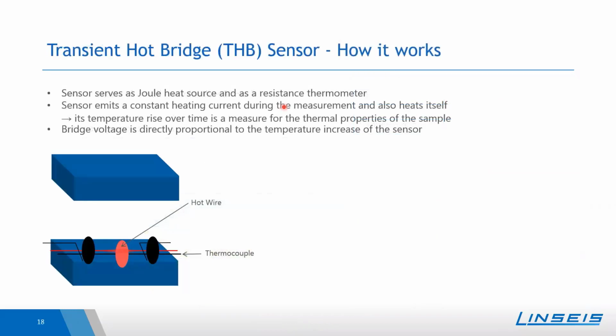But how do these sensors work? The sensor serves as a Joule heat source and a resistance thermometer. So within the Kapton foil, there are some wires embedded, which will heat the sample using a heating current, and due to that, the sensor is also heated itself, and the recognized temperature rise over time is then a measure for the thermal properties.